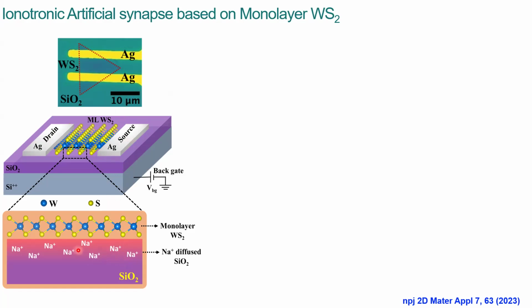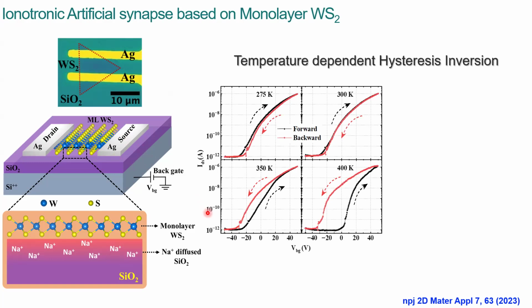diffuse Na+ ions into the initial region of the silicon oxide. So these Na+ ions are mobile in this region, but they cannot go through the bulk. We call it Na+ diffused SiO2, and this is pure SiO2. And this is the monolayer WS2, and on top of monolayer WS2, we have these drain source electrodes. These kinds of ions are temperature sensitive, so we can increase and decrease the device conductance by using temperature.